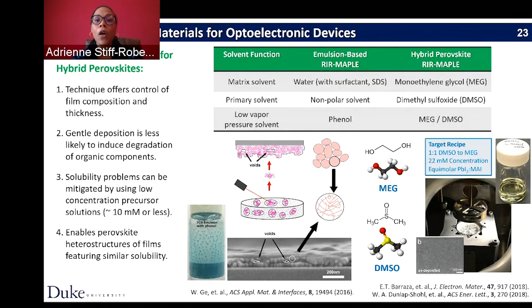You can actually have very low solubility solutions and still get reasonable film thicknesses with MAPLE. And that's important because often, especially when you go to the larger organic molecules, it can be difficult to have the inorganic and the organic part in a single solution. But because MAPLE can have a much lower solubility for that solution, you can still sometimes get them in a single solution together. And again, it can enable heterostructures of these films, even though they might have the same solubility.